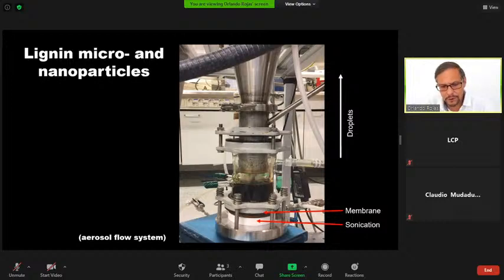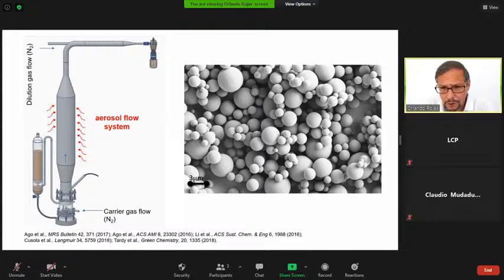And then by surface tension, the lignin solution becomes spherical droplets. And then eventually they become spherical particles. So this is what is illustrated here. And several reports from our group have shown the properties of these nanomaterials that are quite interesting for a number of applications. So I'm very keen about seeing the use of lignin micro and nanoparticles in the future.